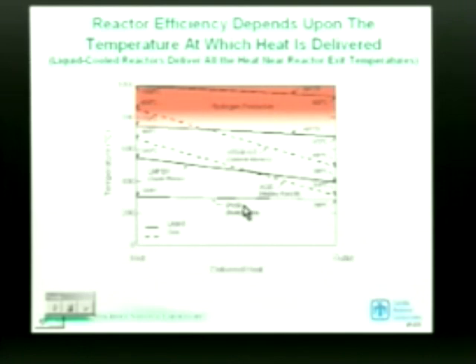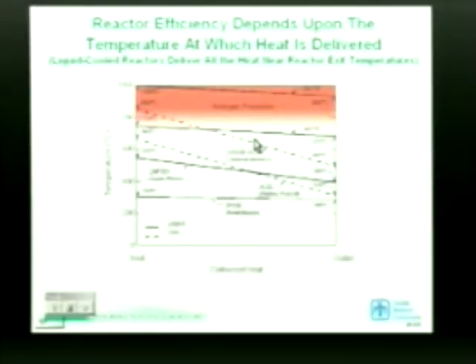Well, what does that mean in terms of our advanced high-temperature reactor with liquid cooling? Let's compare our advanced high-temperature reactor operating at 750 C with a proposed high-temperature gas-cooled reactor operating at 850 degrees C. So we'll give the HTGR a 100 degrees C advantage over us. Well, the HTGR certainly delivers a lot of heat, delivers the initial heat at 850 degrees C, and then the next heat a little lower until we get down to 491 degrees C. If you look at the average temperature of the heat delivered by the HTGR, it's down there about 700 degrees Celsius average.